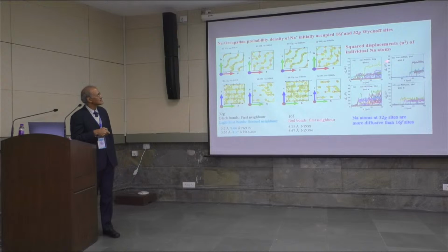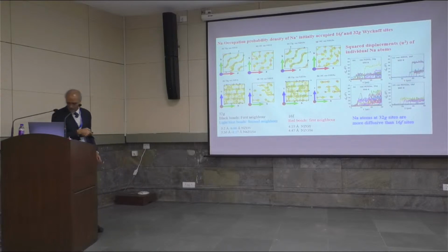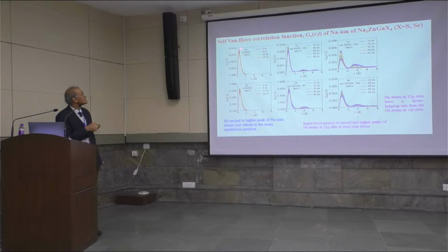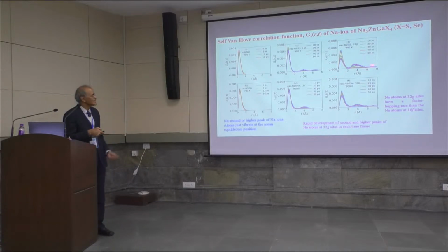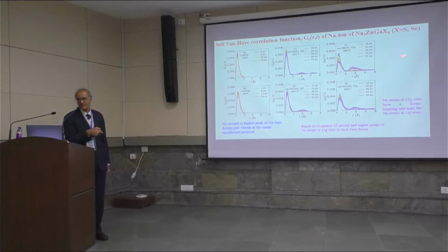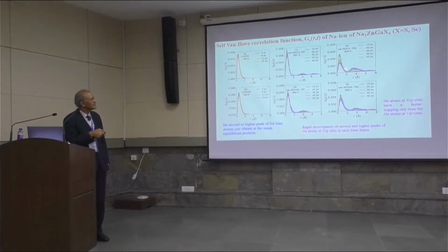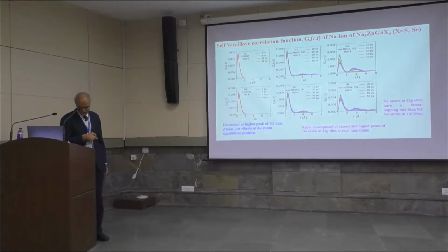Because these are again detailed snapshots of how the jump dynamics takes place and what the time scales are, from studies done this way. Okay, this is again the self-correlation function that tells how, for example, as a function of time, the second peak develops. So the first peak is the self-correlation of the atom as a function of distance from the initial position at zero time. So in the beginning, you have just the phonon kind of vibrations, and as time proceeds, the atom would have jumped to another site at a distance, and then the same atom at a later time is located at a different position again. So this helps us to identify what the jump lengths and jump times are in this process.